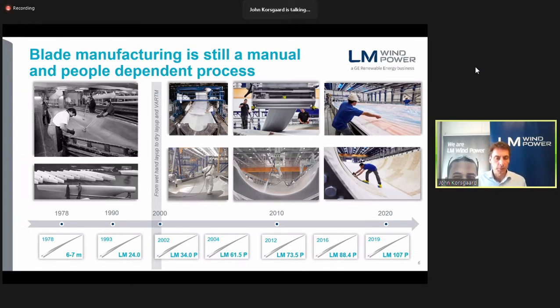The manufacturing process was still wet hand layup, but we started to see some of the limitations of this manufacturing process. There is some limitation of how much glass you can put into the mold before the resin starts curing, and you needed to break up the layup process a number of times in order to put in the full laminate.